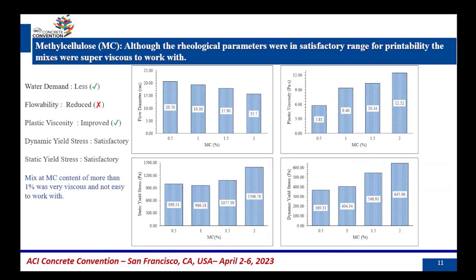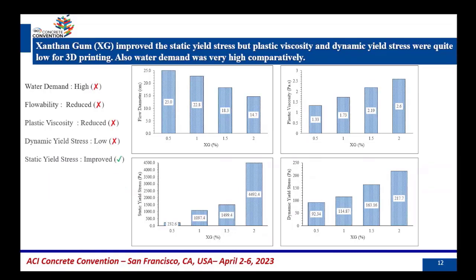case. And also methyl cellulose, although all the rheological requirements were in the printability range, when we added methyl cellulose content more than 1% weight of cement, the mix was very viscous, so it was not easy to work with that mix, and it was not easy to print that mix. Finally, with xanthan gum, the water demand was quite higher. The static yield stress was improved, but again the plastic viscosity and dynamic yield stress were very low.